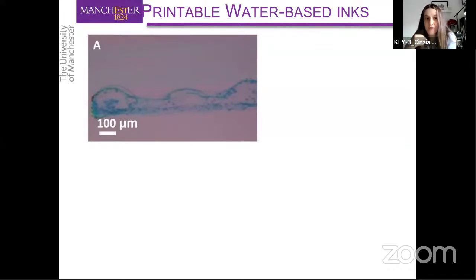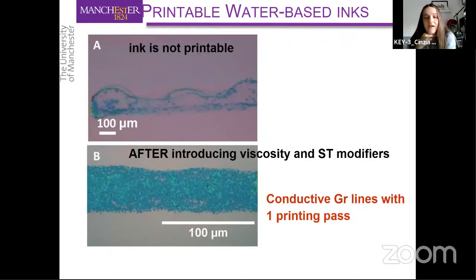And so in particular, we know that water is not a good solvent because of its rheology, but then it's very easy to change its surface tension and its viscosity by adding some modifiers. And this is exactly what we did. We lowered surface tension and we increased viscosity by using certain additives, and at the same time we further increased the concentration by removing all the pyrene molecules that were not absorbed on graphene by introducing a further centrifugation step after exfoliation.